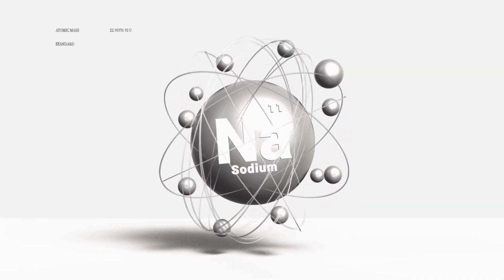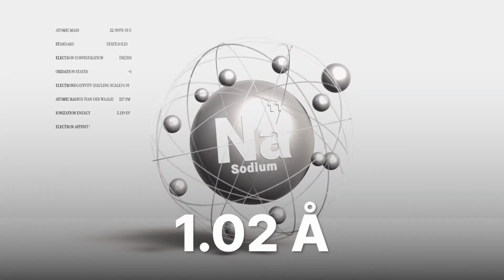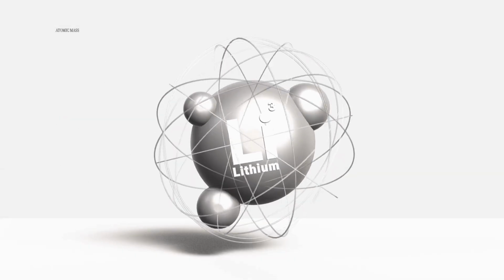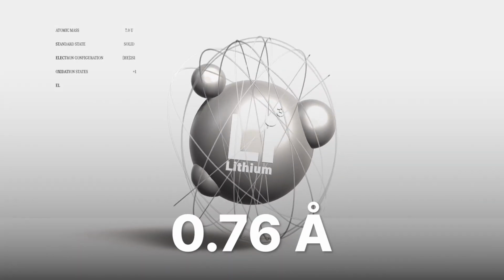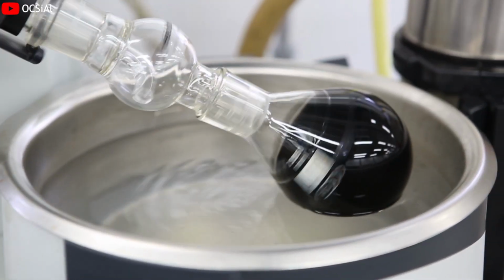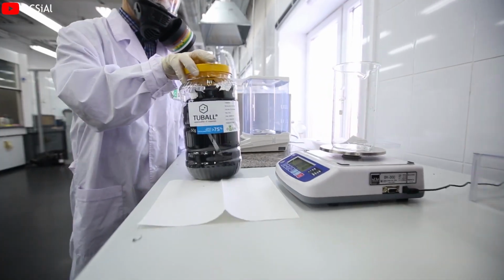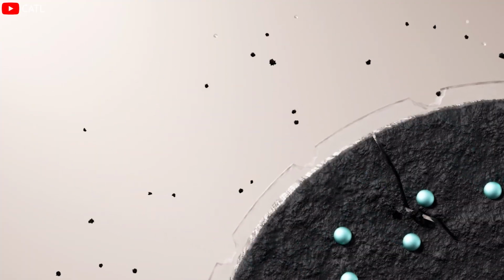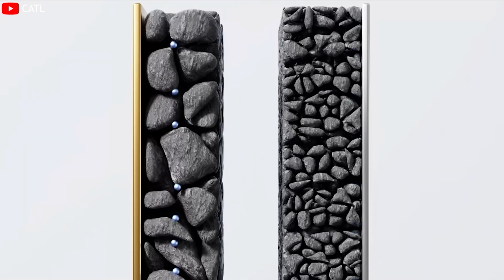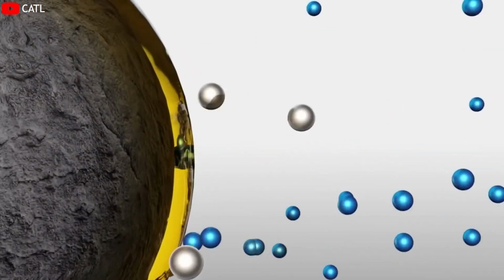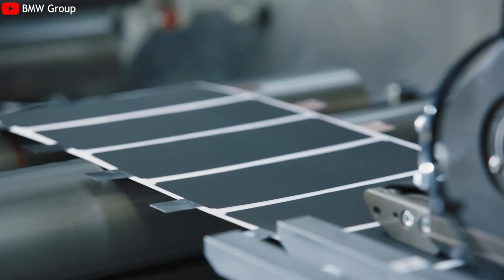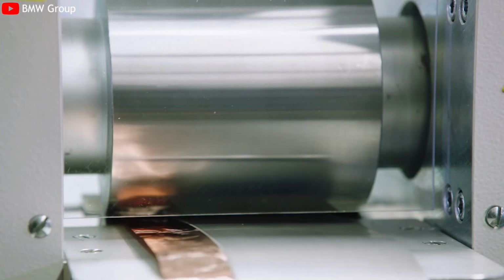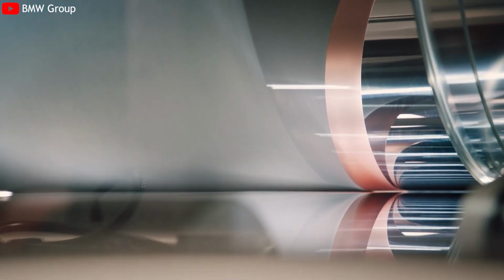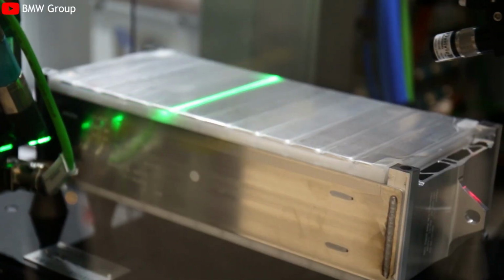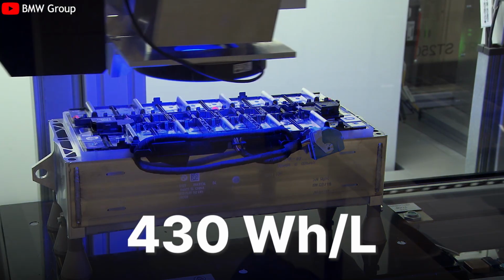Sodium ions have an atomic radius of approximately 1.02 angstroms, compared to 0.76 angstroms for lithium. This is not a technology gap. It is a physical limit. Larger ions require larger host structures, thicker electrodes, and more inactive material. The consequence is unavoidable. Sodium-ion batteries achieve around 300 watt-hours per liter, while commercial LFP packs already reach 430 to 450 watt-hours per liter.